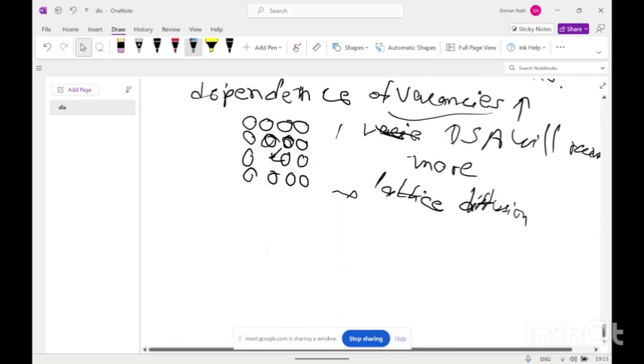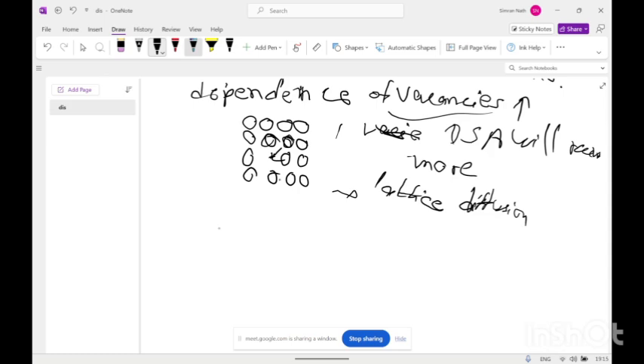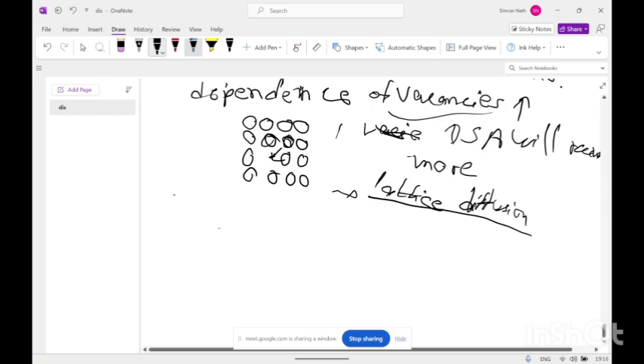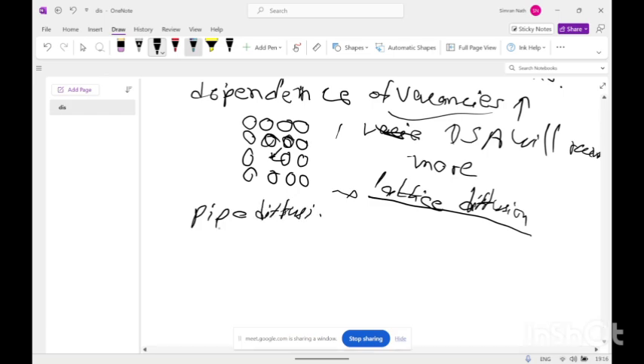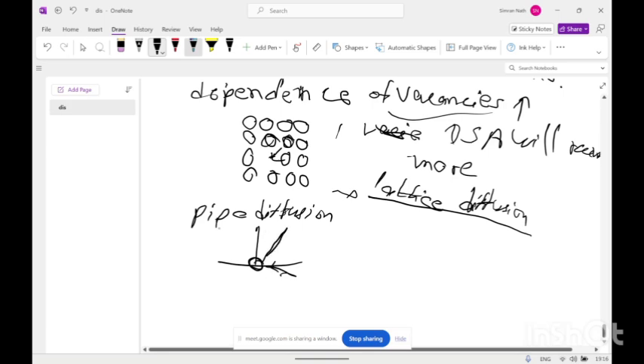The dependence of vacancy on dynamic strain aging is that the diffusion because of the vacancy is called lattice diffusion. But there is one more type of diffusion, that is pipe diffusion, that occurs along the dislocation core. This is the dislocation core. So the diffusion along the line forms a pipe. The region looks similar to a pipe, so that's why it's called pipe diffusion.